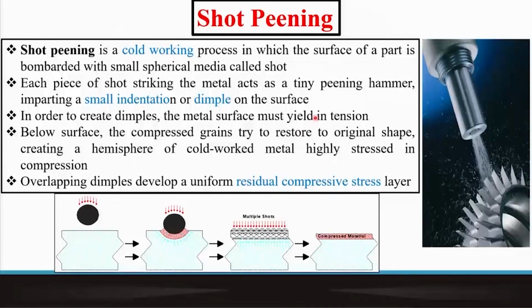So when we see such cracks, then we realize that on moving parts or dynamic parts of engineering components, particularly which are in deep rotational service at high RPM, or they undergo complex variation of stress cycle in association with temperature or any other activation, then the surface requires a certain amount of special attention in terms of preparation before they are actually put in use. So how do you take care of them? And this is where surface engineering processes like shot peening come in very handy.